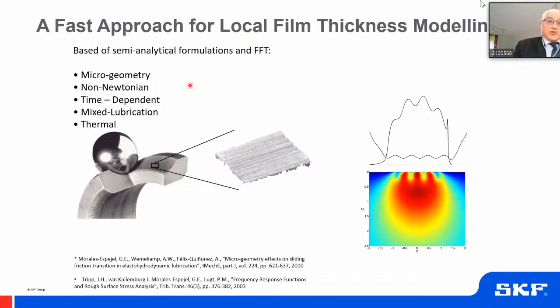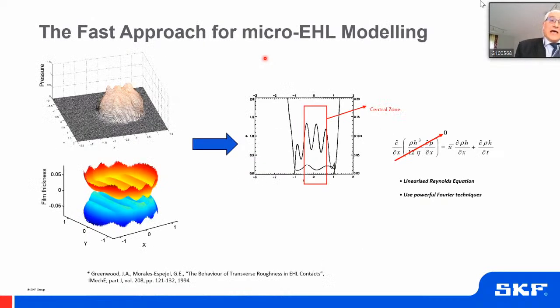Models that can actually consider the microgeometry of the contact, that also can model the non-Newtonian behavior of the lubricants, time-dependent solutions, mixed lubrication, and thermal effects, and actually modeling the whole topography in a contact. Now, to do that, we have to rely, as I said before, on semi-analytical solutions based on fast Fourier transform. And I would like just to give you a brief idea of the concept. The actual model is a bit more complicated than this, but this is just to show the basic idea. If you have two surfaces which are rough and are lubricated, they will produce a pressure distribution that has these pressure ripples. Now, we do not want to model the whole geometry of the contact because that is very time consuming. We want to focus on modeling the ripples only, the pressure ripples and the film thickness ripples.